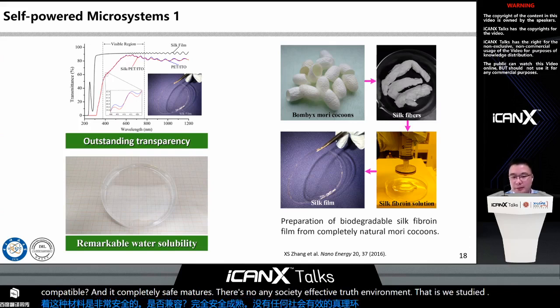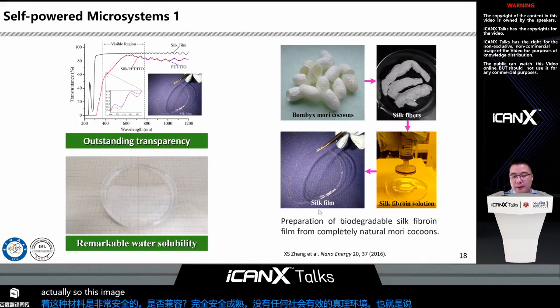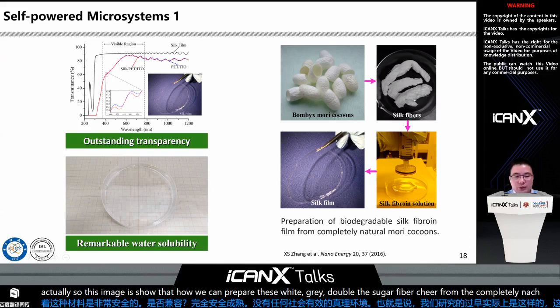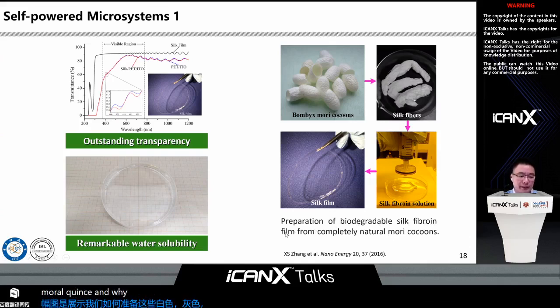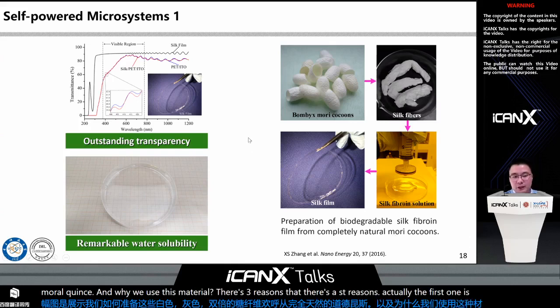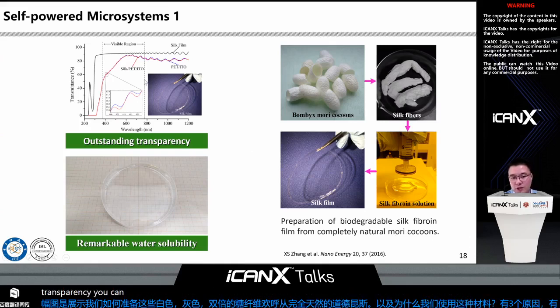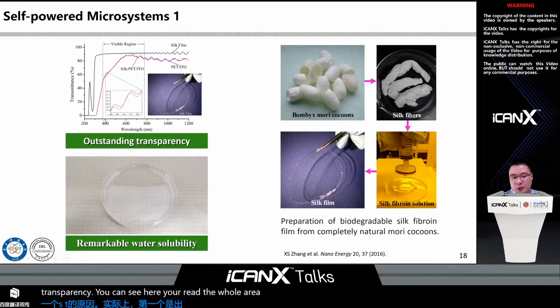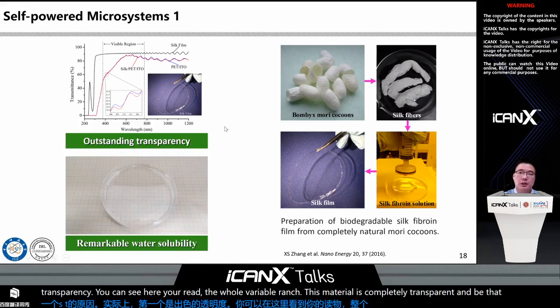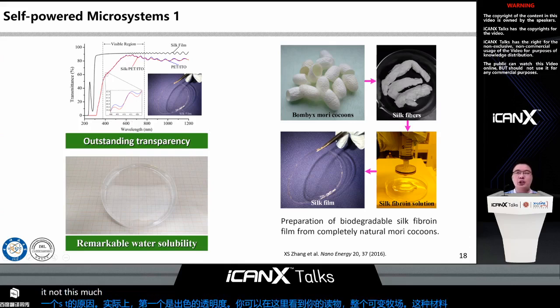So this image shows how we can prepare this biodegradable silk fiber film from the completely natural mulberry cocoons. And why do we use these materials? There are three reasons. The first one is outstanding transparency. You can see here, over the whole visible range, this material is completely transparent. It means that you can use these materials to cover some devices without changing the optical properties of the devices.